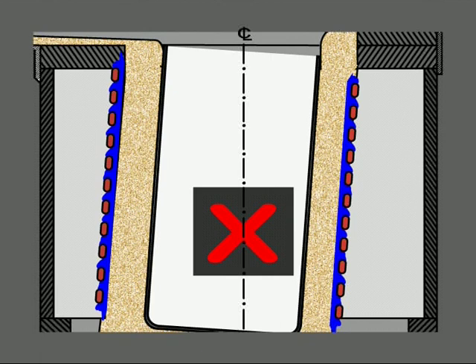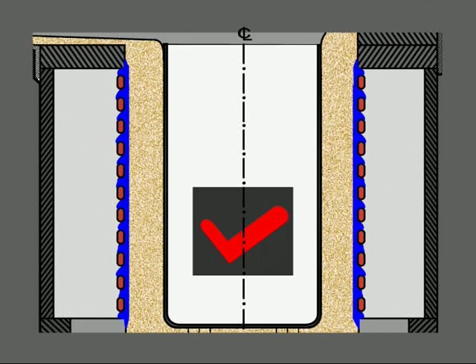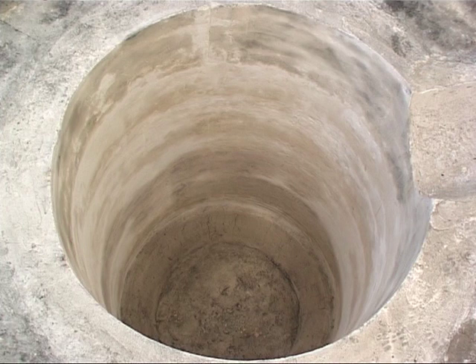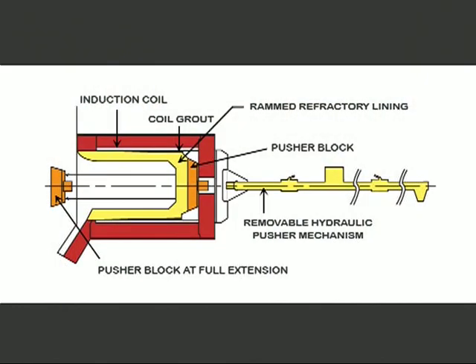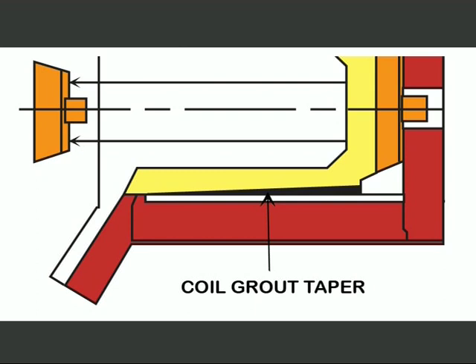Vibration causes segregation of the particles, resulting in pockets in the partially sintered lining. If the coils have been changed, make sure that they are concentric with the furnace structure. Coil grout should be applied with minimum water for troweling and not more than 3 to 5 mm thick in smaller furnaces and 5 to 10 mm thick in bigger furnaces. For furnaces where the hydraulic push-out method for lining removal is adopted, adequate taper should be given to help in removal of the lining. What are the properties of a good coil grouting cement?